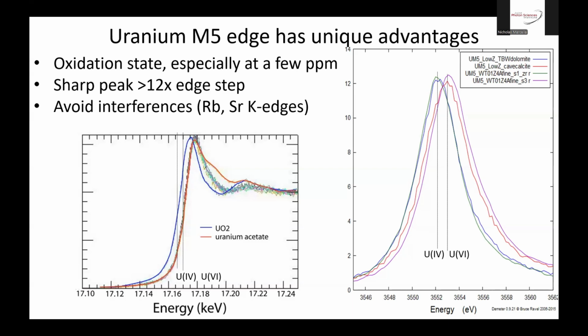And so this is really good for making distinctions between uranium-4 and 6 at very low concentrations, because we've done this down to a few ppm. You have to use like analyzer crystals for this? No, just an ordinary fluorescence energy dispersive detector.